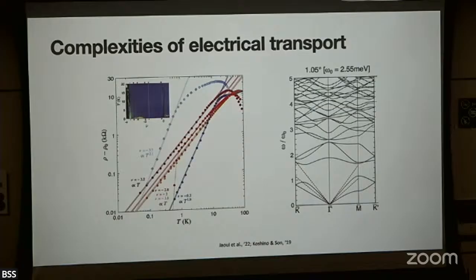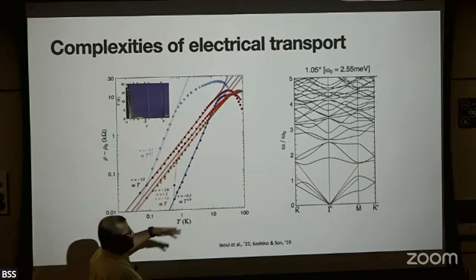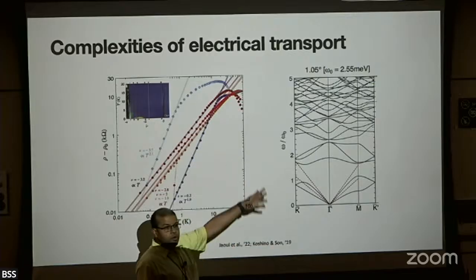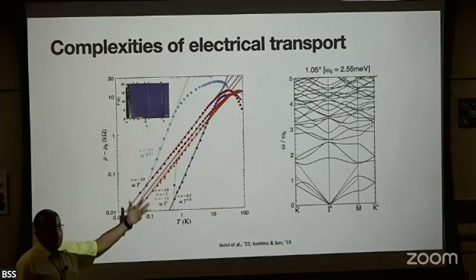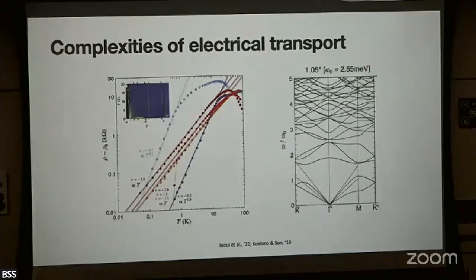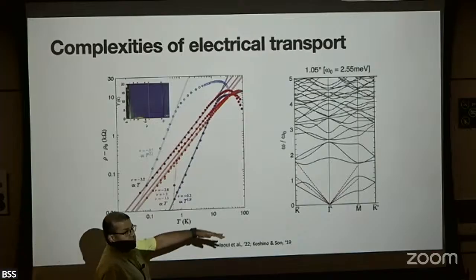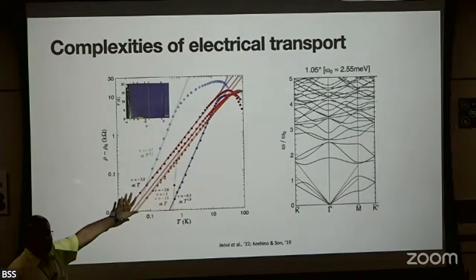And just for the sake of concreteness, this is what you would calculate for what the phonon dispersions might look like if you start from just the individual phonon modes in graphene and twist them, add the Moiré potential, they get reconstructed. So again, there's a whole bunch of phonon modes. If transport was determined by some kind of Matthiessen's rule, then you would expect there to be all kinds of crossovers as you go up in temperature, and yet you don't see any of that.